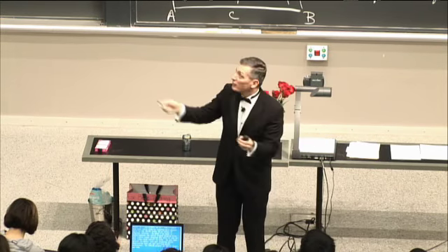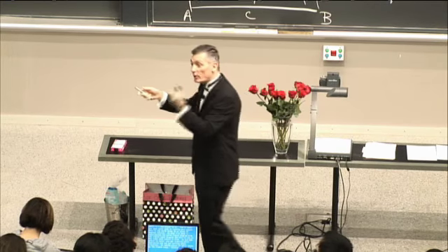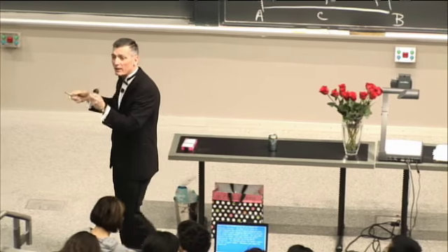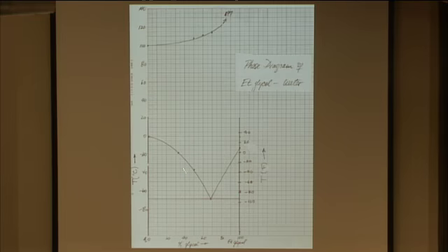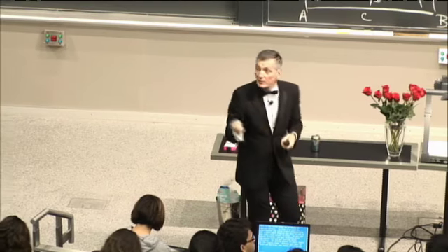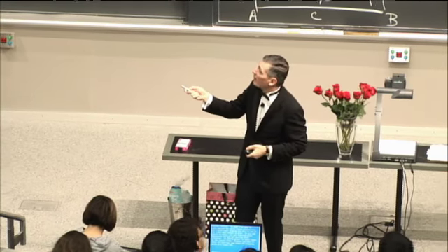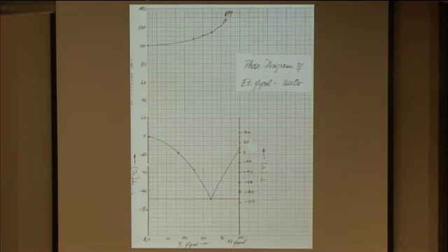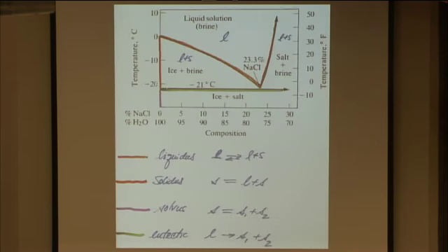And because you want to stave off boiling, because boiling will cause lousy cooling and the engine will overheat, and you want to stave off freezing, which will cause the ice to form and crack the engine block, you get both. And then you put the pressure cap and then jump this up to about 265 degrees Fahrenheit. So this is a very good example of management of the properties of the coolant through chemical change. And the binary phase diagram eutectic type is a critical piece here.